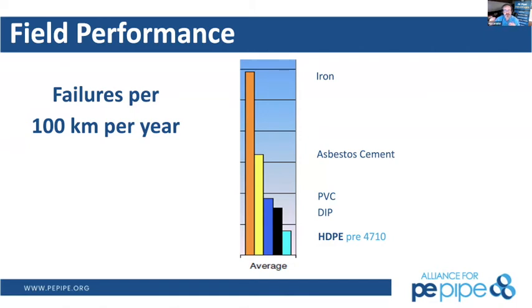Because of the occasional recurring surge pressure resistance that the advanced HDPE pipe material has, we're able to withstand those operational parameters of routine pressure surges, valves on and off, or all valves shut down. PVC doesn't have that accommodation of higher pressure surges within the material itself. So it suffers from cyclic fatigue, and a lot of these failures in the 20 and 30-year-old PVC are cyclic in nature. Alan, I've got another question for you.